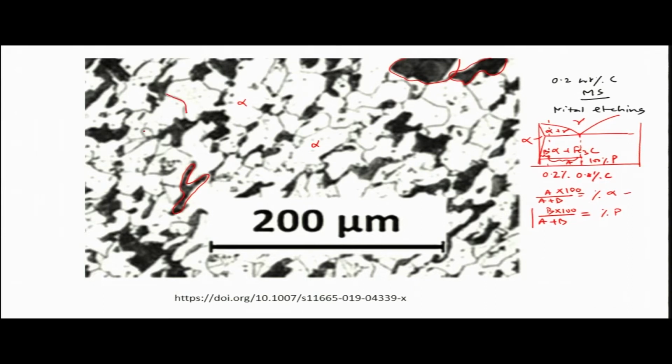So, these are the grain boundaries, and these grain boundaries have evolved due to the mechanism I explained in the last lecture, that there is a preferential dissolution along the grain boundary. So the profile looks like this, and there will be light rays falling here, and there will be multiple reflection, and then finally the light comes to the eye. That multiple reflection of the light leads to reduction of the strength of that particular light ray. So, that is what it becomes, grayish in color or black in color.